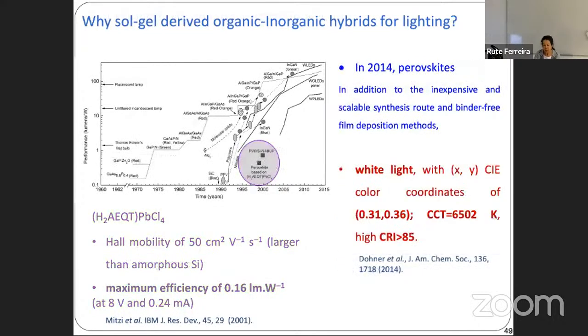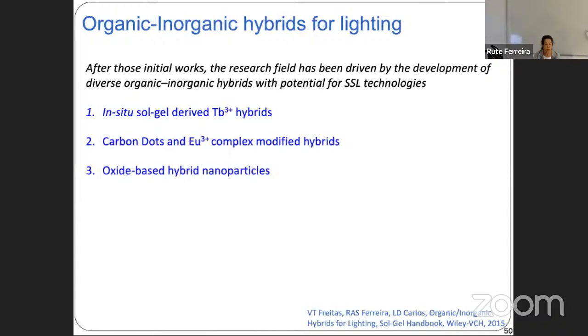But in any case, those first examples revealed white light color coordinates with quite interesting values, with CCT above 6,500 Kelvin and very high color rendering index above 85. After those initial works, research in the field has been driven by the development of diverse organic and inorganic hybrids with a huge potential for lighting technologies. Here I will highlight 3 examples: in situ sol-gel derived terbium-based hybrids, carbon dots and europium complex modified hybrids, and finally I will address the case of oxide-based hybrid nanoparticles.